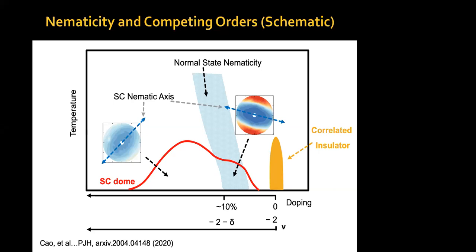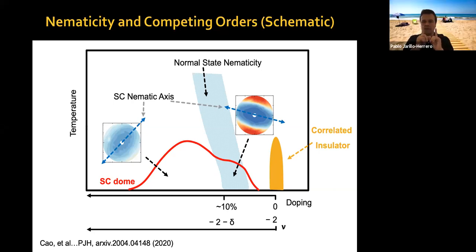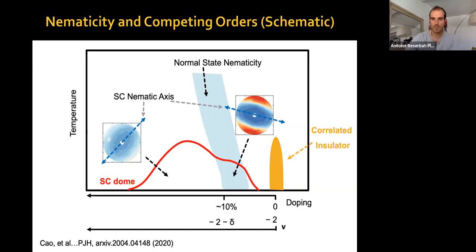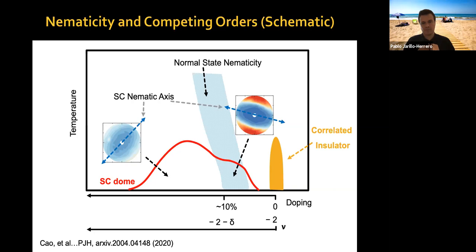Yes. These things are not, you know, it's not that one is different from the other, in the following sense. These are two different things. Nematicity tells you that you go from whatever lattice rotational symmetry your crystal had, fourfold for a square lattice, threefold, sixfold, whatever lattice rotational symmetry you had, to twofold. You choose a direction. You have an ellipse in your properties, only one axis of symmetry, C2 symmetry. So you choose a direction.